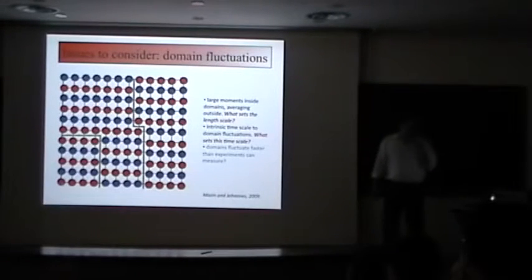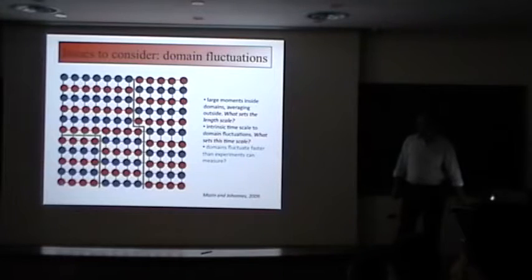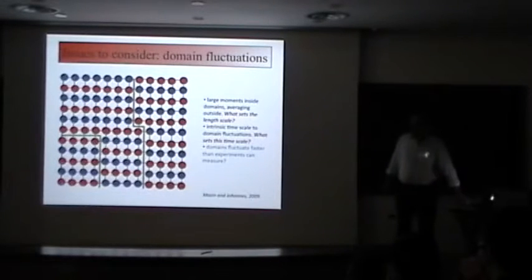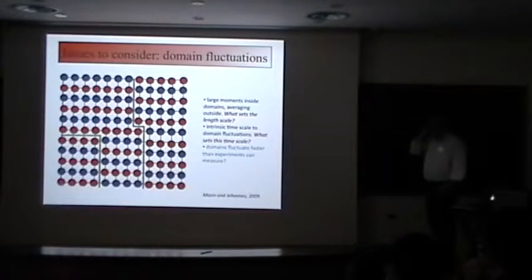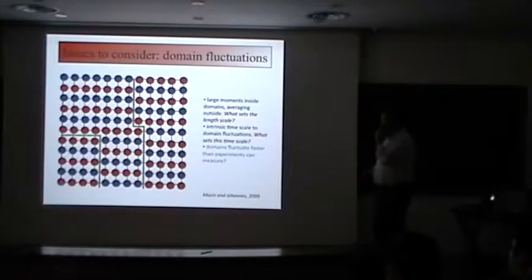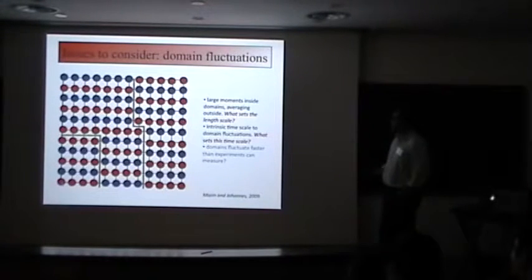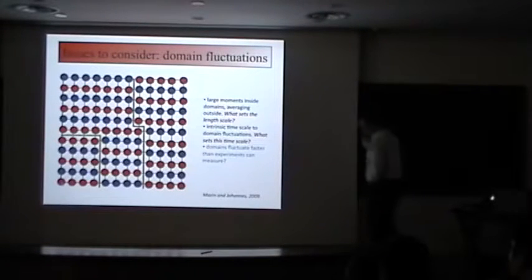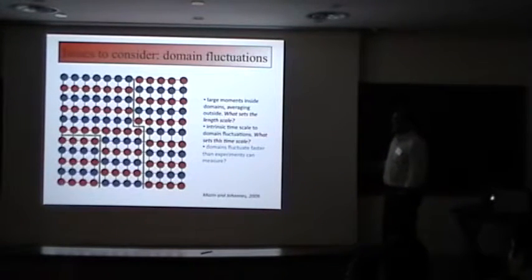So one of the things that has been discussed is how can we bring these moments down. One area raised is domains which can possibly be formed, in which things are antiferromagnetic with large moments inside a particular domain, but for some microscopic reason we don't yet quite understand, the system likes to go into longer regions which on average point in different directions and give a much smaller average effective moment.